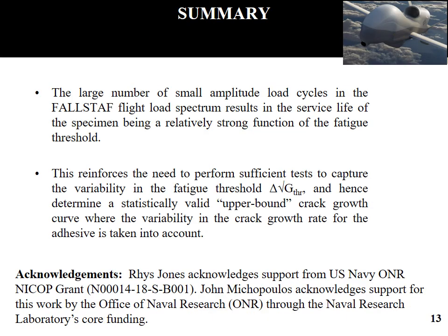The large number of small amplitude load cycles in the FALLSTAF flight load spectrum results in the service life of the specimen being a relatively strong function of the fatigue threshold. This reinforces the need to perform sufficient tests to capture the variability in the fatigue threshold and hence to determine a statistically valid upper bound crack growth curve where the variability in the crack growth rates for the adhesive is taken into account.